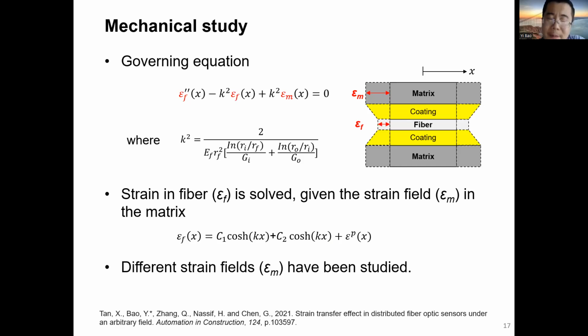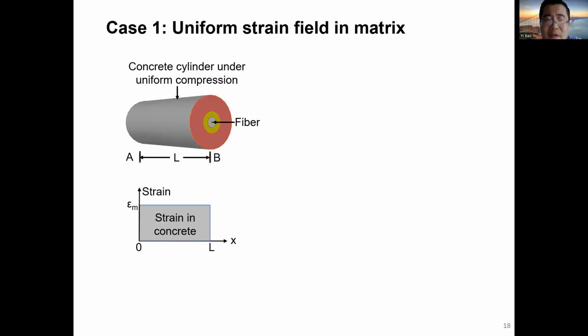But we focus on solving the problem for distributed sensors with a very long length. And because of the long length, the strain field for the fiber sensor at different length distance could be different. So we derived this governing equation, and then we try to solve this governing equation by defining the boundary conditions. First, we consider the simplest case, which is uniform strain field.